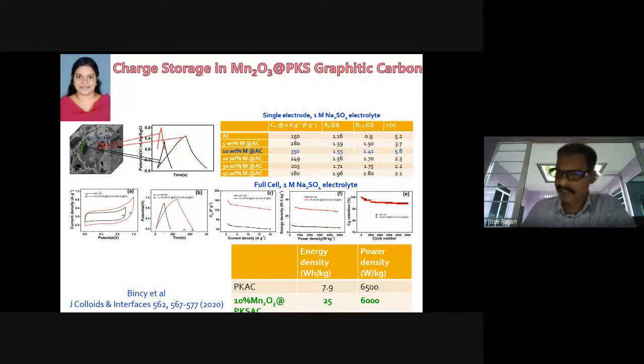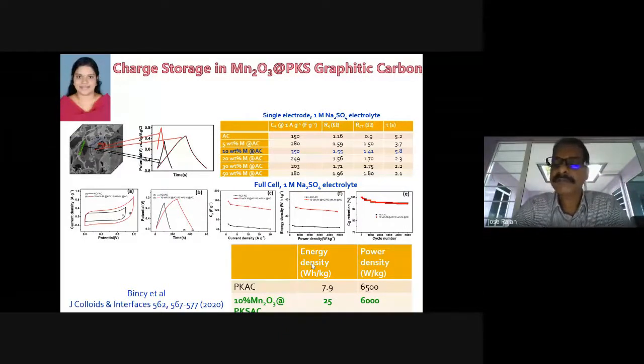I can share this slide later so that you can browse the details. Looking at the table at the bottom, the energy density and power density of pure palm kernel shell and metal oxide coated palm kernel shell are compared. Energy density refers to how much charge can be stored. Power density is how quickly it can be charged or discharged. In the case of pure carbon, the energy density is about 8 watt-hour per kilogram, something similar to or a bit higher than commercially available supercapacitors.